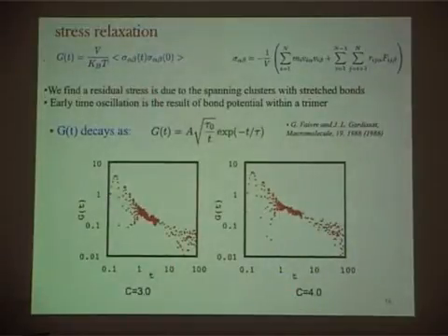Okay, so then we compute the stress and look at how the stress relaxation happens. That's what has been shown here. Stress relaxation follows the 1 over root t exponential minus t by tau. Again, this 1 over root t comes from the fact that there is this scission and recombination, so that has been worked out in this paper here. We see the same, that we can fit our curves into this function. Of course we have these oscillations here, which come from the bond, the spring oscillations. That's the reason for this.